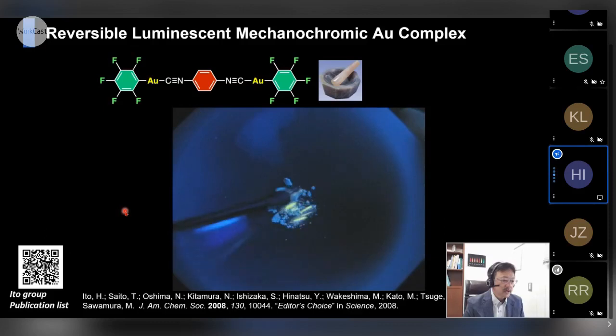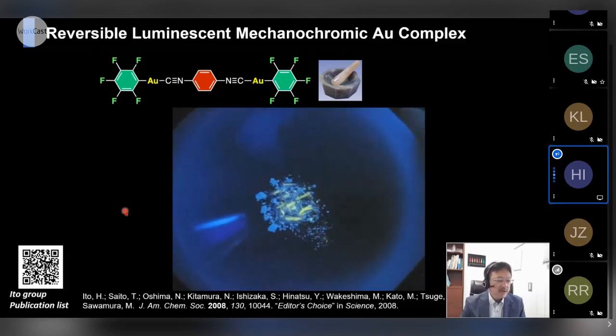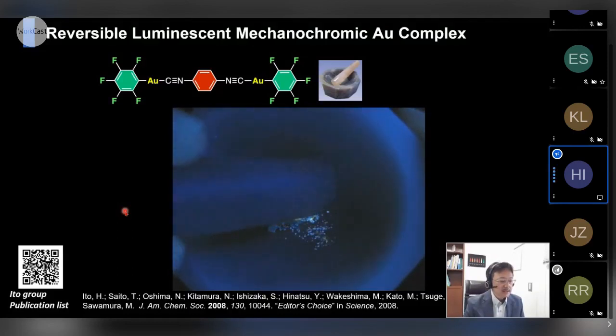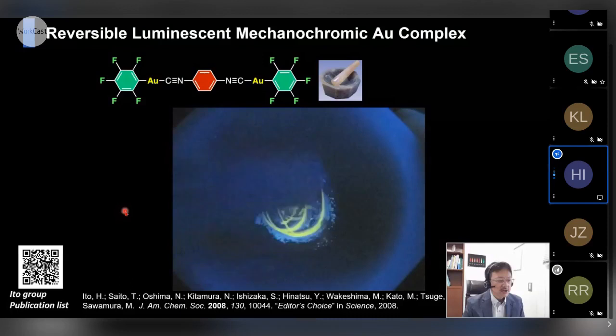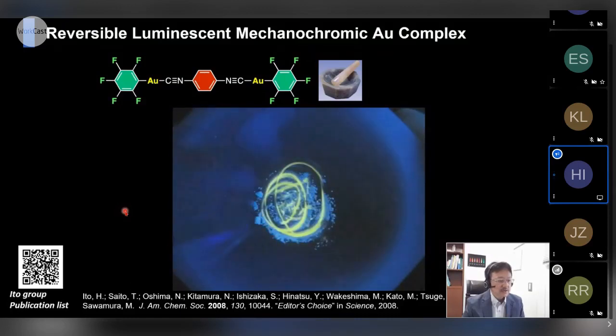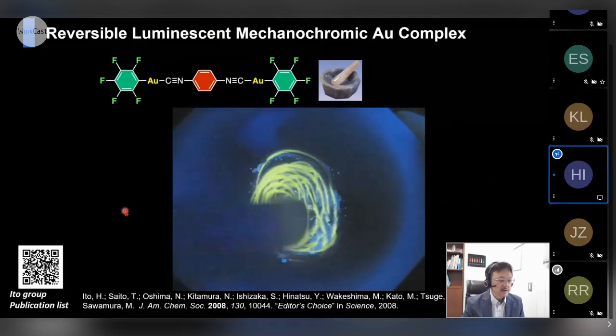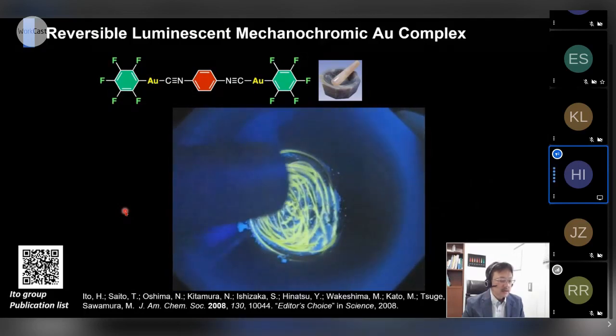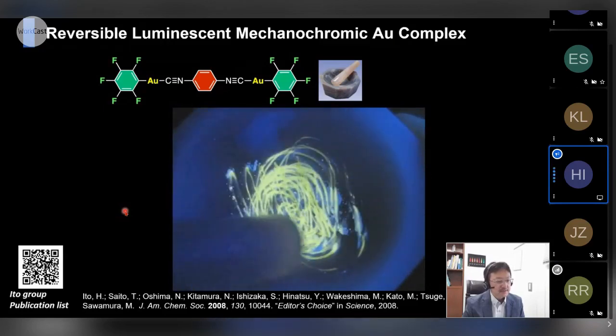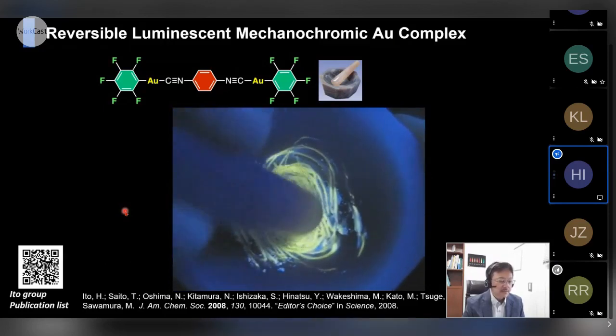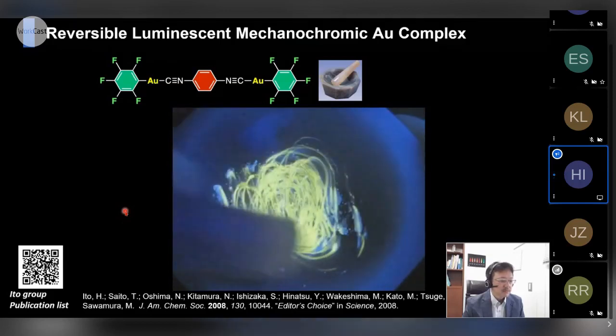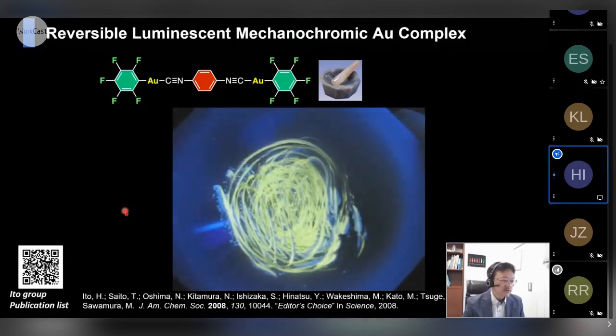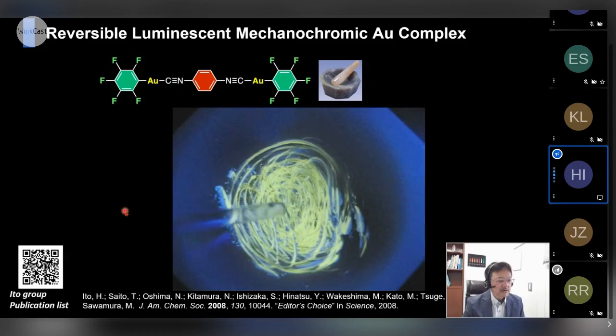If you add mechanical stress on the surface of this compound, you can see a very rapid color change from blue to yellow. This is a very typical mechanochromic luminescence property. And if you use a larger agate mortar and pestle, you can see a more drastic color change from blue to yellow as shown here. We found this phenomenon about 14 years ago, but now this mechanochromic property is very popular. Many researchers have reported similar things, but I think this is almost the first example of reversible mechanochromic luminescence.